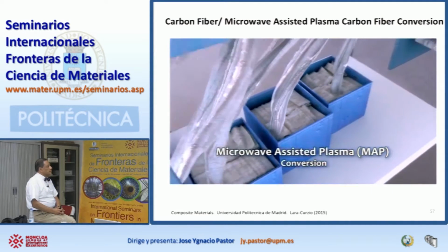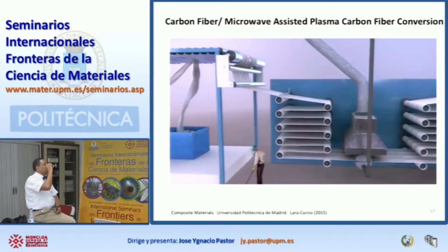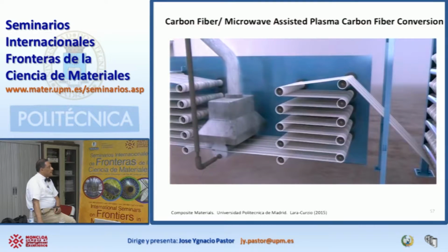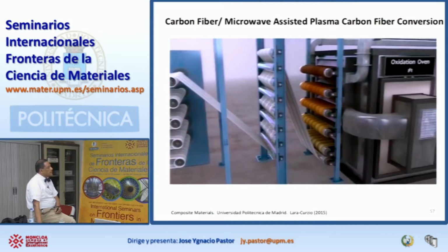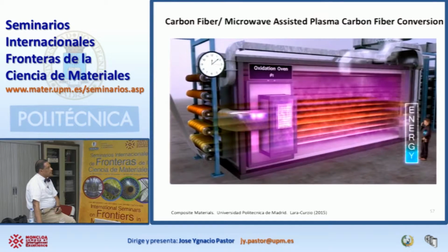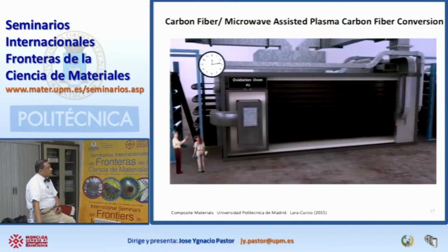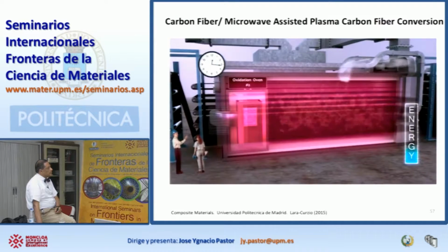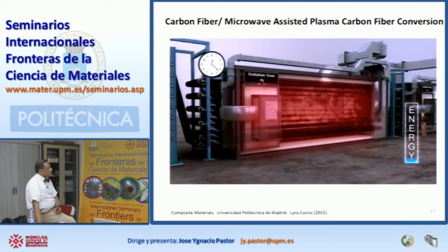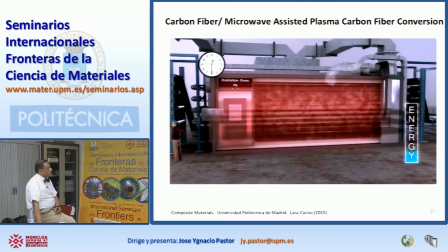During the microwave-assisted plasma, or MAP, conversion process, crimped or spooled PAN fiber feeds into the pre-treatment module and proceeds through a steam heating and stretching process. The fiber enters an atmospheric pressure plasma oxidation module, darkening from white to black as it weaves through the first of several oxidation ovens. The number of ovens can vary based on production needs. Inside, the atmosphere is controlled and air temperature is lower than with conventional processing. The special chemistry of the atmosphere accelerates oxidation.